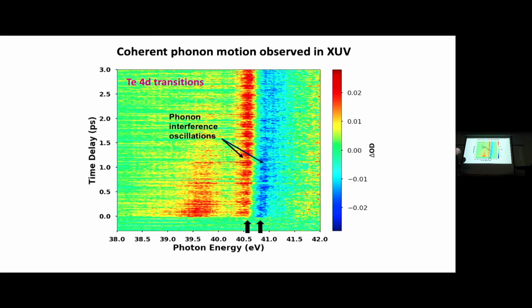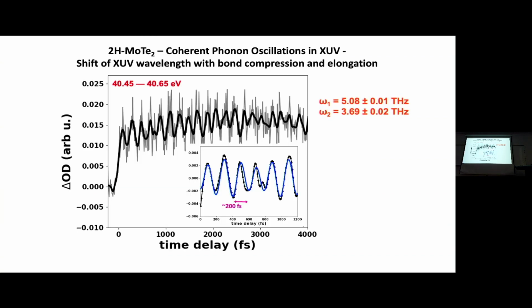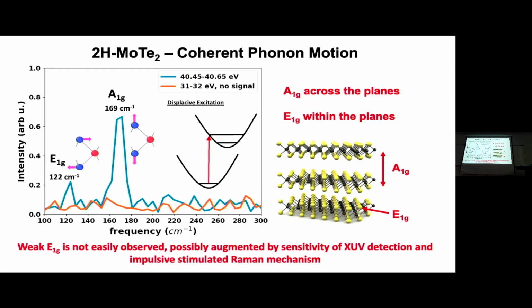So here is a blow up of these coherent phonons. You can see it's bright, it's weak, it's bright, it's weak. And we can get the phonon periods out and see which modes are playing a role, and they're coherent in this case. If not, we would not see this modulation. So if we take a line out of this data, we can fit it or do a Fourier transform and find there are two frequencies, one around 5 terahertz, one around 3.7 terahertz, that are underlying this coherent phonon motion. Here's the Fourier transform, and we can assign through the known Raman spectra, the higher frequency is the A1G mode, and the lower frequency is the E1G mode. And here they are, from the data, just doing the Fourier transform.